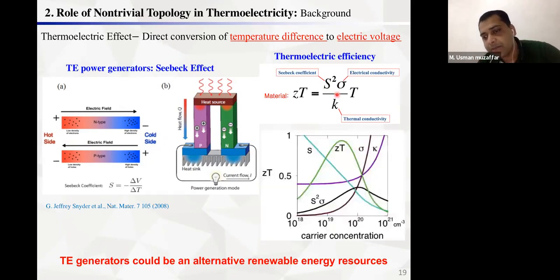You can see from this figure, this is the carrier concentration as a function of ZT. ZT is the figure of merit, the efficiency. With the increase of the carrier concentration, you can see that the electrical conductivity increases, while the Seebeck coefficient decreases. So one increases, the other decreases. So the power factor, the product of these two, will lie somewhere here, which will be the trade-off between these two quantities.